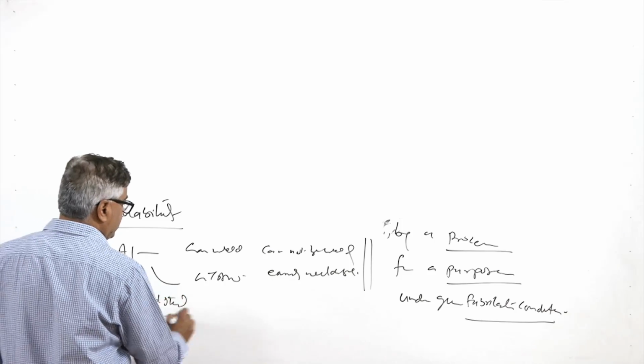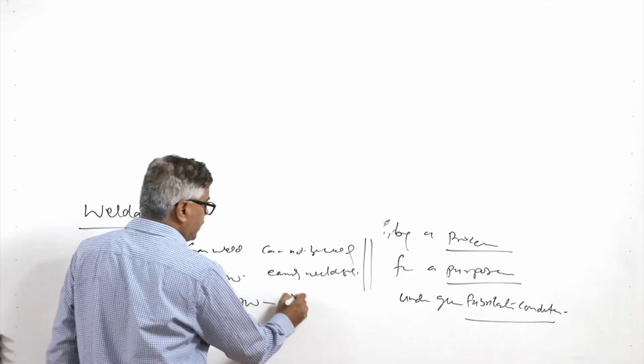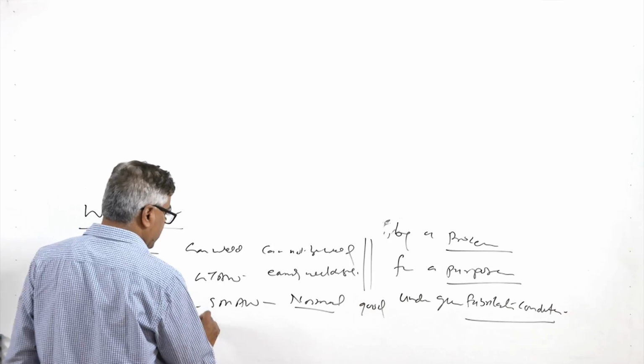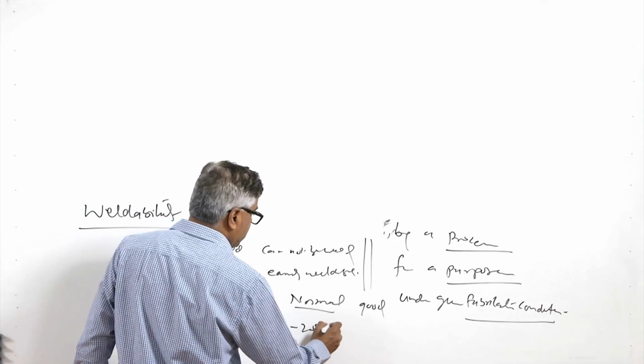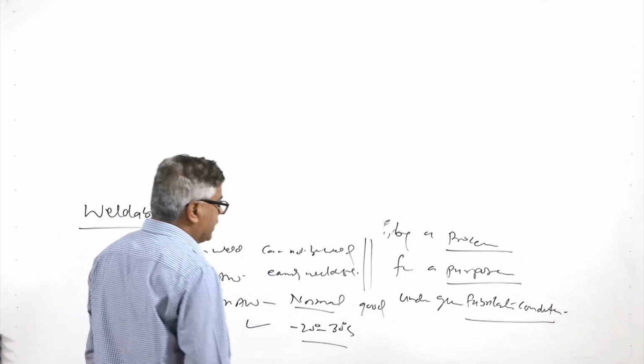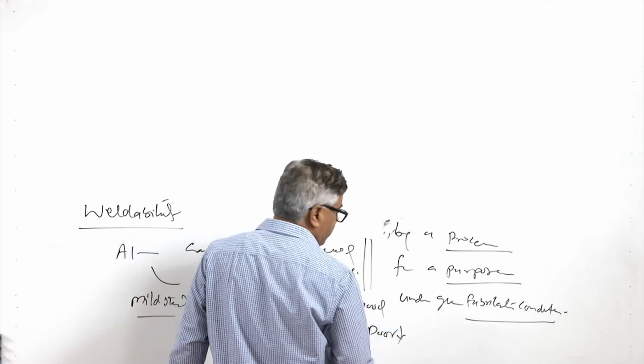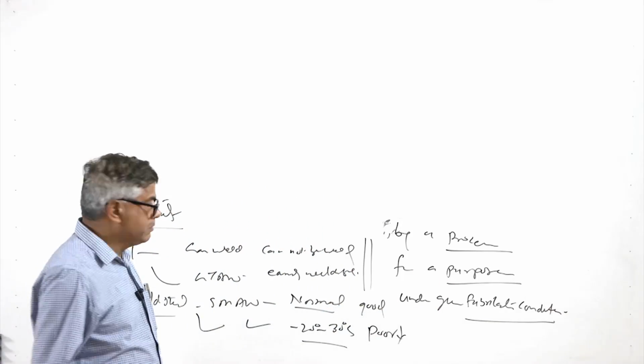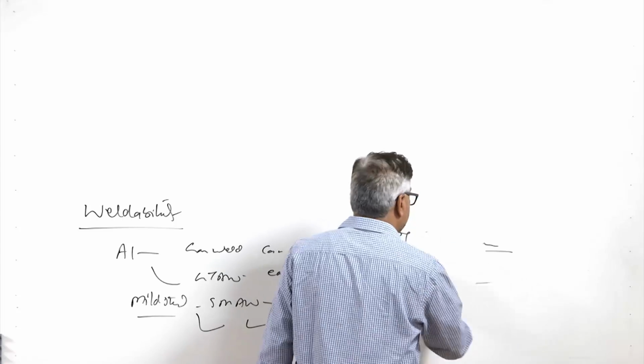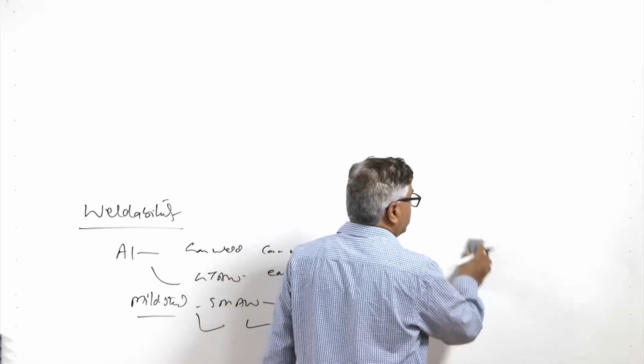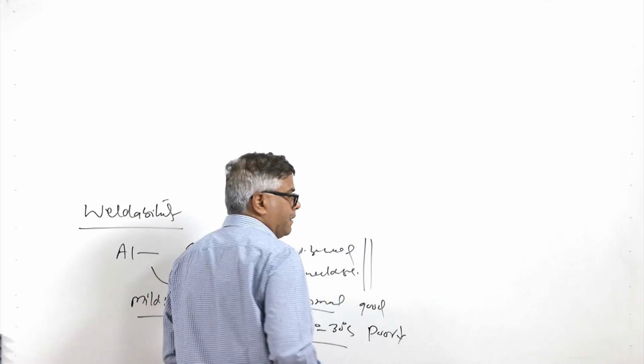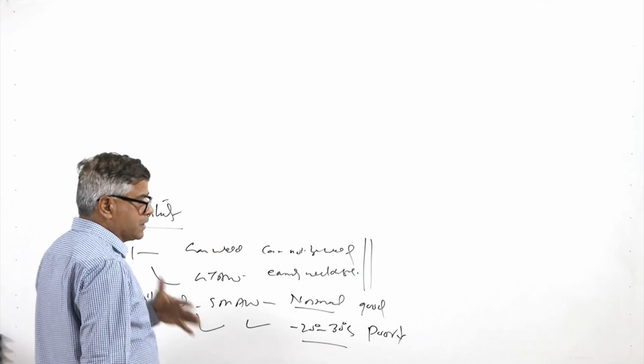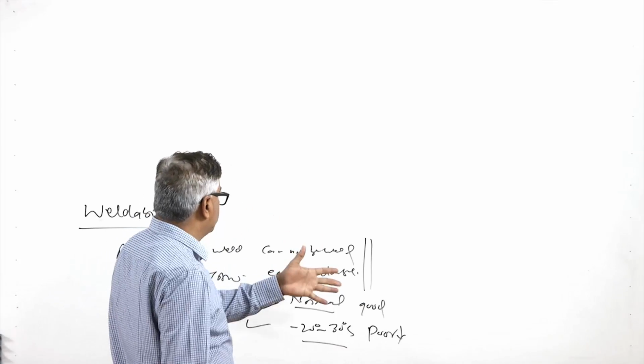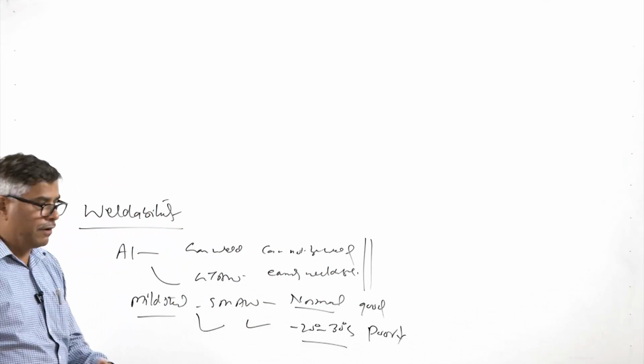So, the process brings in the difference in the ease of welding, that is why we specify the process. And then the purpose, like say mild steel welded using the simple shielded metal arc welding process for normal room temperature conditions, its weldability is good. But if the same joint is used at minus 20 or minus 30 degrees centigrade under impact conditions, this kind of joint is very poor, because there is a great loss in the toughness of the joint under sub-zero temperature conditions. So, it is important that the function for which the joint is to be made, and the fabrication conditions, meaning the kind of procedure to be followed, are fixed. If all those are fixed, then it will be easy to define the ease of welding for a given metal.